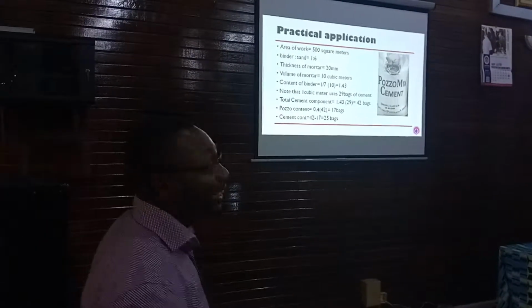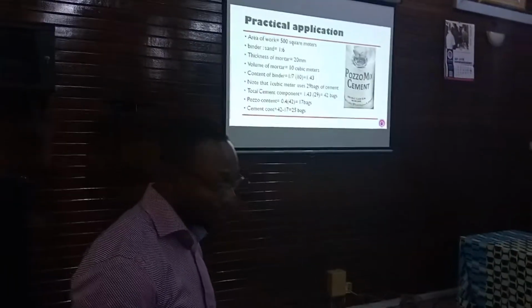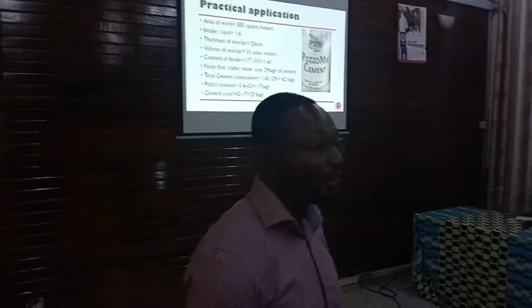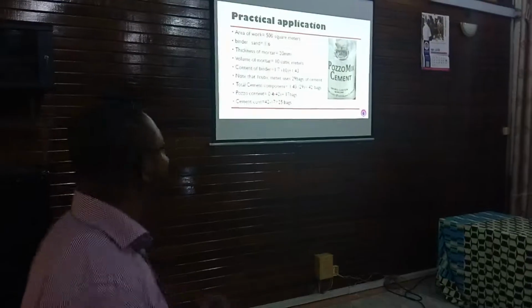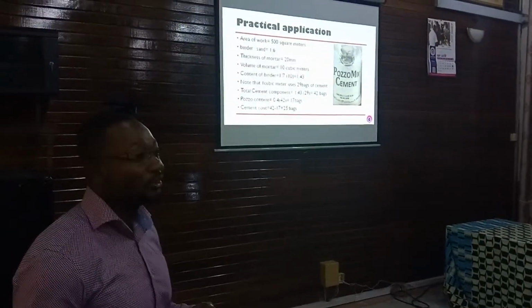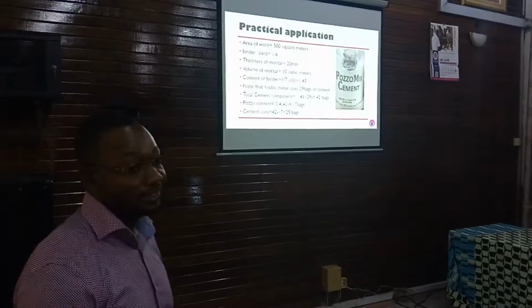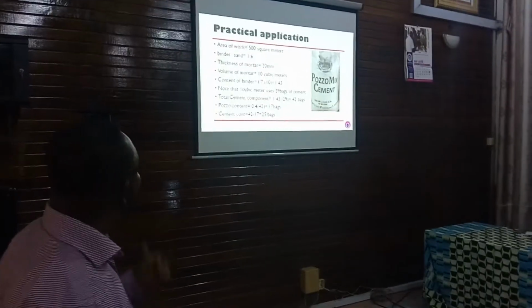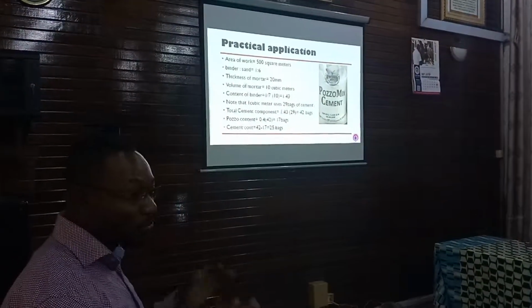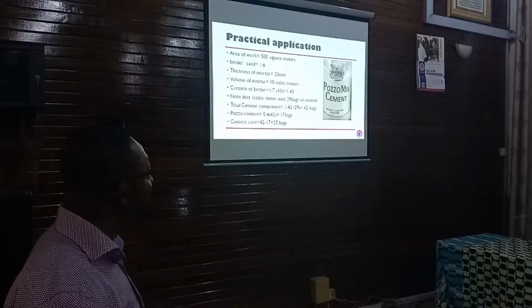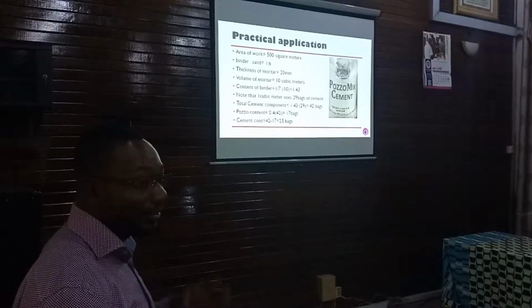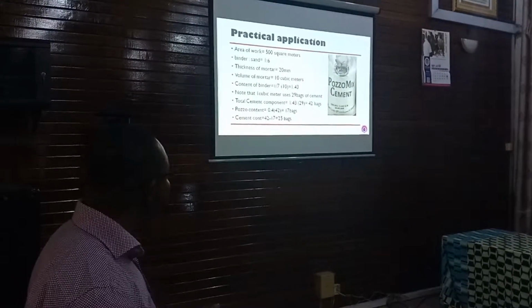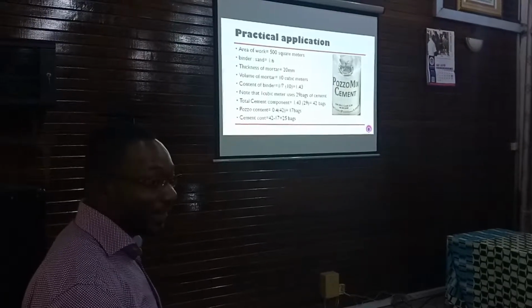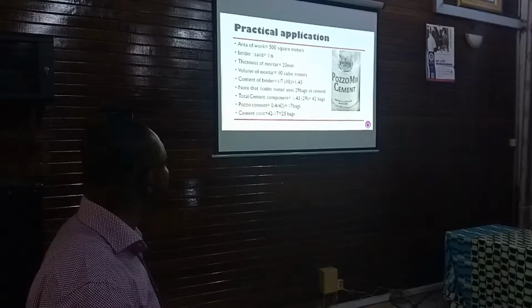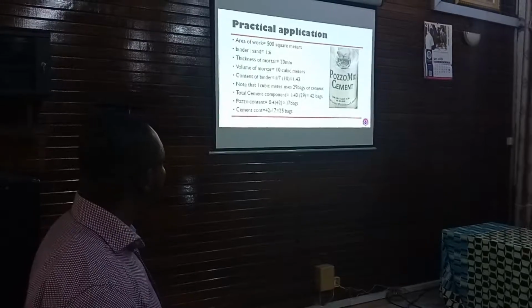The binder to sand, usually it is 1:7, but in the lab it is a little different, 1:6. Now, the thickness of the mortar was 20 mm. Sometimes people use 14 mm, but averagely it is 20 mm. So it means that the volume of the mortar that I will be producing in the field will be 10 cubic meters if I look at the area and then the thickness. Then the content of the binder that I will use from the ratio is 1.43 meter cube.